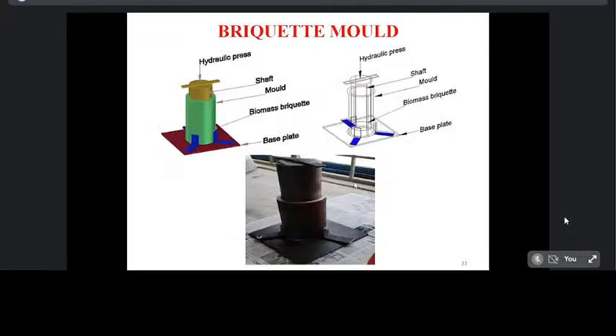After setting all the initial things, that means the agricultural waste material collected and initial pre-processing are completed, the starch solution is also prepared, and sun drying and grinding are all completed. After all the basic things, we are going to prepare a briquette mold. A cylindrical briquette mold was used, having an inner diameter of 80 mm. Three parts are here. First the top portion is a shaft, then the center portion is a mold, and the bottom portion is a steel plate. The diameter of the cylindrical mold is 80 mm, the thickness of the mold is 8 mm, and the height of the mold was 150 mm.